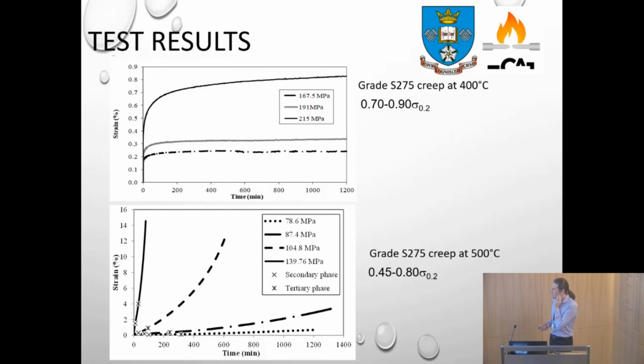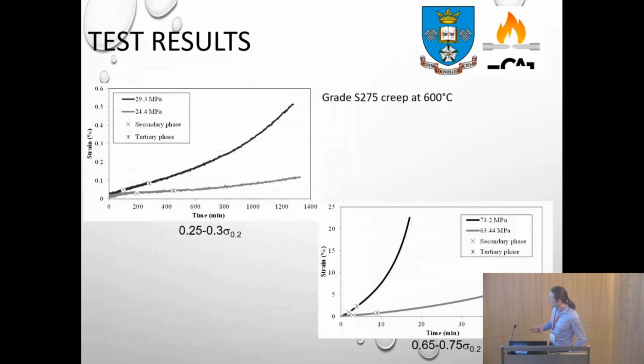As far as the creep test results that we made on coupons, at 400 degrees at high stress levels, we have a prolonged primary creep phase, so there is a very slow creep development occurring with respect to time on the coupon level. At 500 degrees, you have to lower down the stress levels and see what happens there. The onset of secondary creep phase occurs very fast in time, as we've seen from the table. At 600 degrees, the onset of secondary tertiary phase comes quite fast in the time domain at lower stress levels.